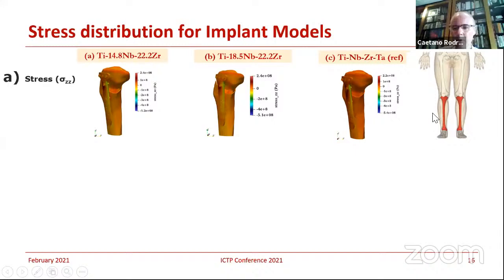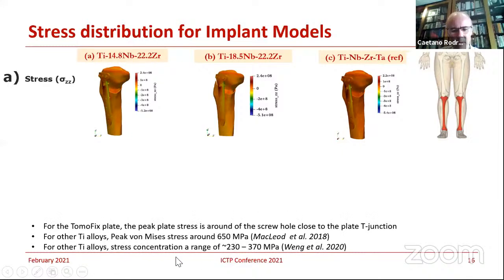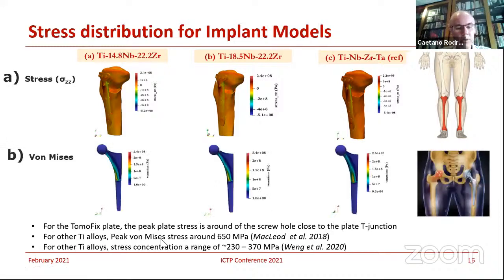So here's the stress distribution for the implants. So you are talking about this region of the bone, and you have this plate that fixes these two parts of the bone if you have a fracture. Now, if you compare the stress response of the alloys that you figured out together with the reference one, basically you have a very similar mechanical behavior. And also, the performance compared with the titanium alloys is much better.